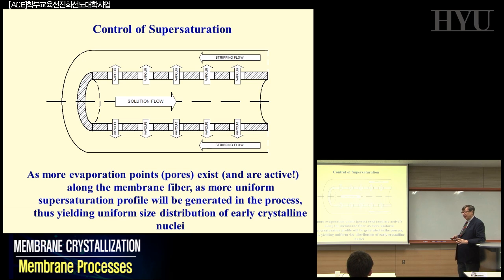So the heterogeneous final result that you have in a normal crystallizer, in this case, by definition, if these pores are as much as possible all the same, in the same configuration, you can control the concentration on one side, the concentration on the other side, the size of the pore, etc. So you have all the parameters controlling the supersaturation, and the crystal formation would be basically point-like. Along the membrane fiber, you can create a very uniform supersaturation profile in the process. That, in principle, was one of the predictions we were making. You can have a yielding of uniform distribution of early crystalline nuclei.